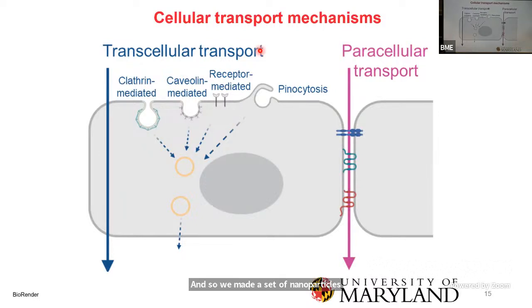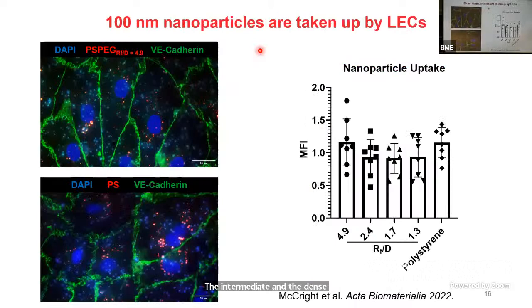And so we first just asked, okay, well, does the surface chemistry actually affect the uptake of the particles? Well, it didn't really affect the uptake. So what we found is that at least for 100 nanometer particles, you can quite clearly see that it doesn't matter whether you're a polystyrene particle or you have some PEG or a lot of PEG. Pretty much the same in terms of uptake. But we do see a difference in transport. So we started honing in on, okay, are there any specific mechanisms that we can tease out?